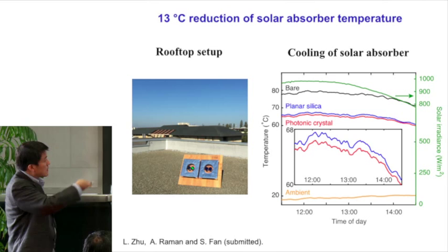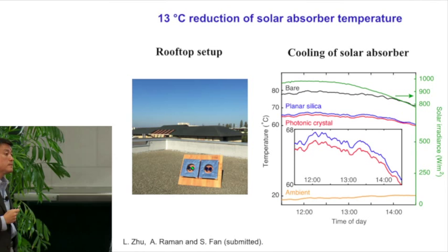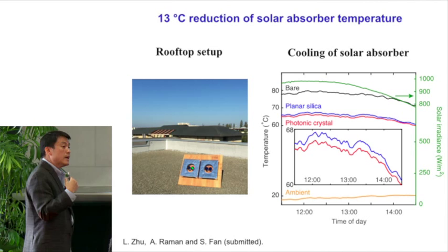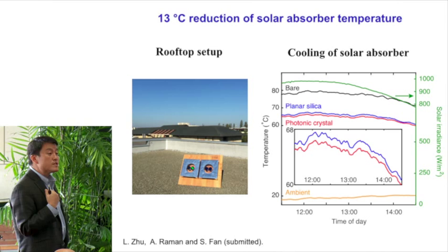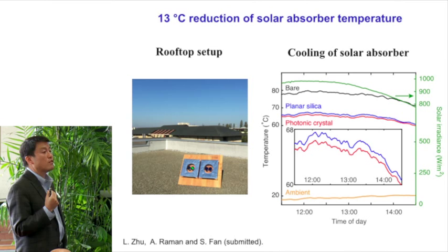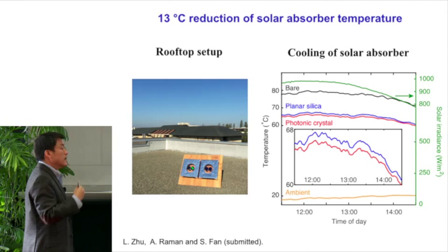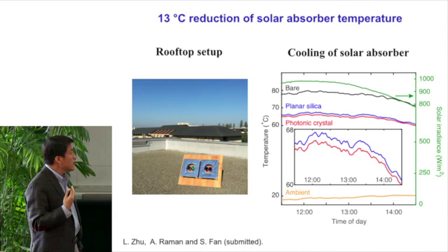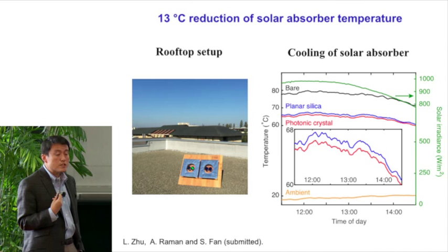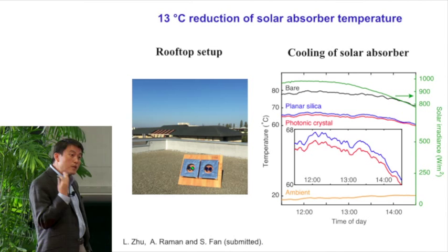The temperature drop here is as large as 13 degrees Celsius. Now, to translate into an estimate of efficiency, if you can cool down a solar cell temperature by about 13 degrees Celsius, this would translate into an efficiency gain on the order of a percentage point, which, as you heard from Homer's talk in the very beginning, even a 0.1 percentage point improvement in silicon solar cell efficiency took an enormous amount of effort. So I think this is actually a very interesting opportunity to do radiation control in order to improve solar cell efficiency in a practical operating environment.